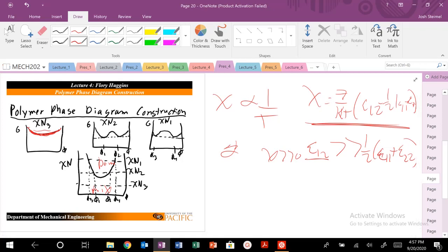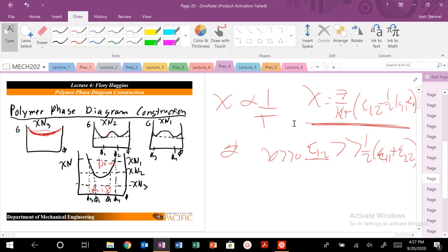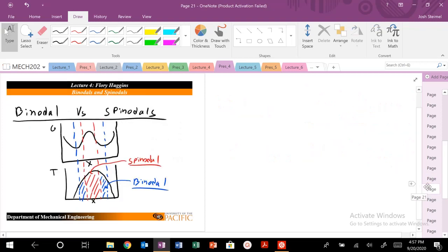I'm in that free energy curve at my lowest state. If I see points of inflection where the curvature changes from positive to negative, I know I have a common tangent — and that's going to give you a hint on what we're going to be searching for today. Thus, I'm going to have a phase-separated region. Just wanted to give that for information.